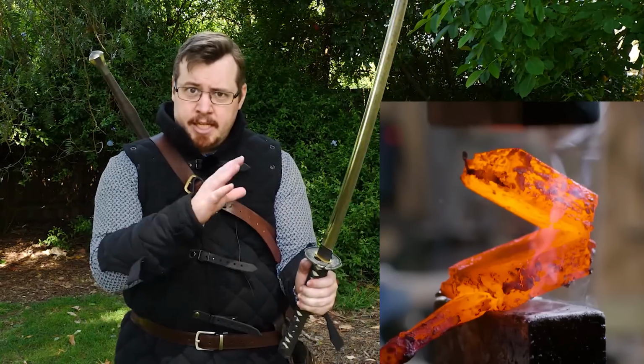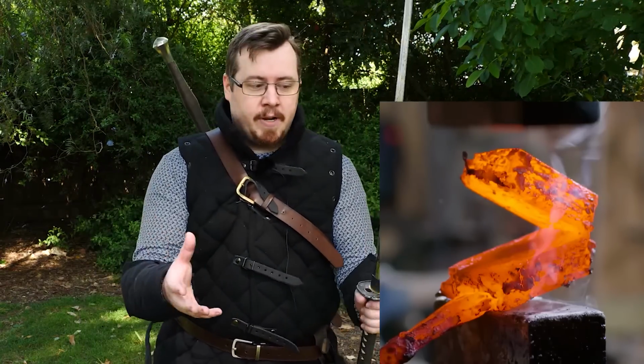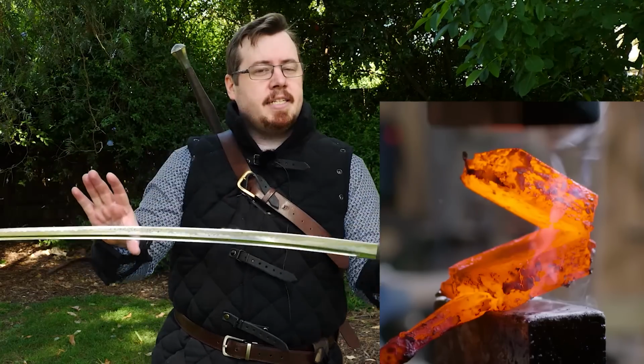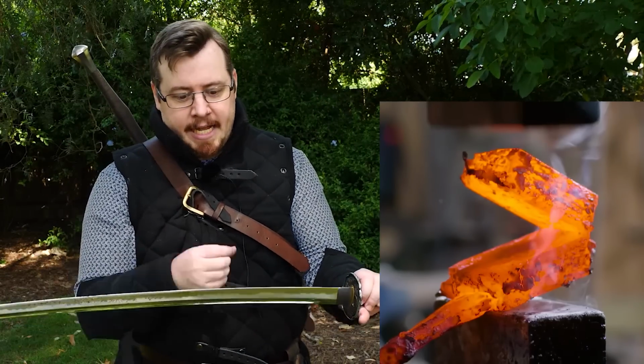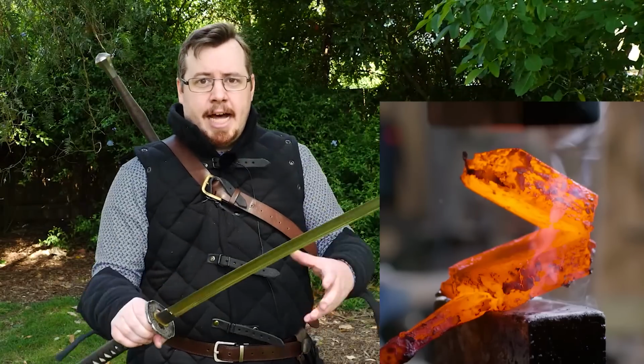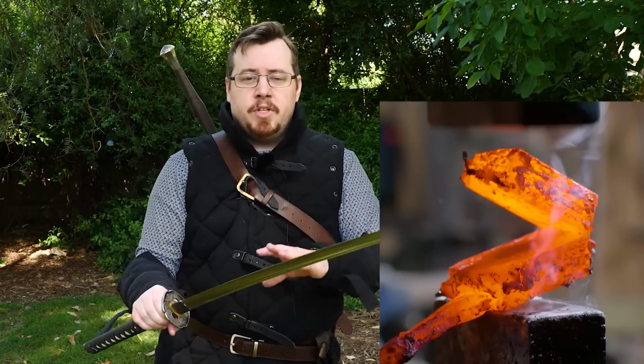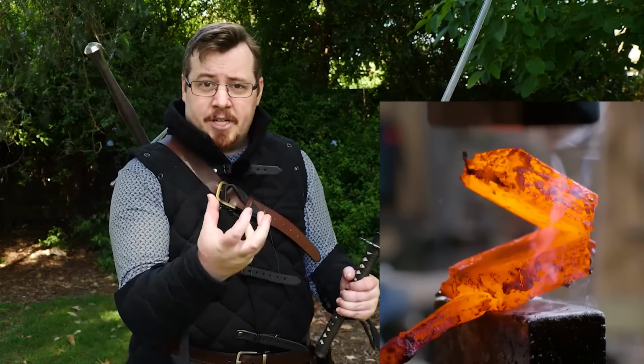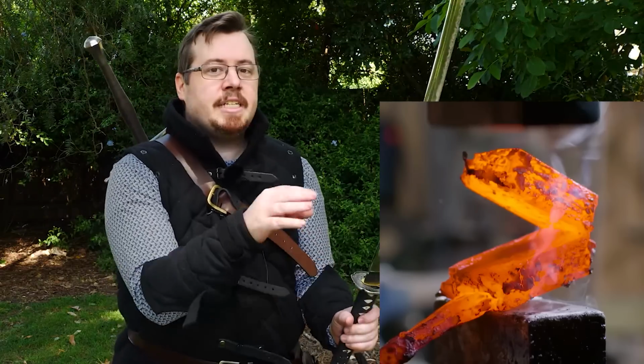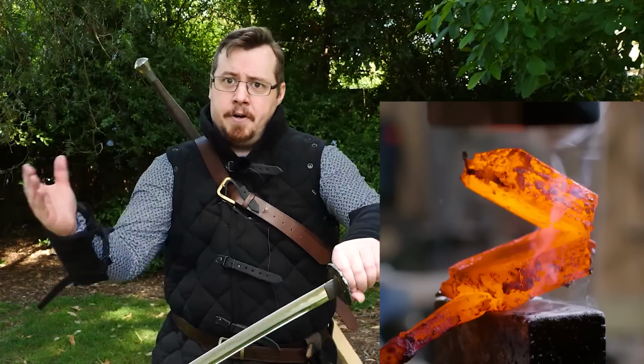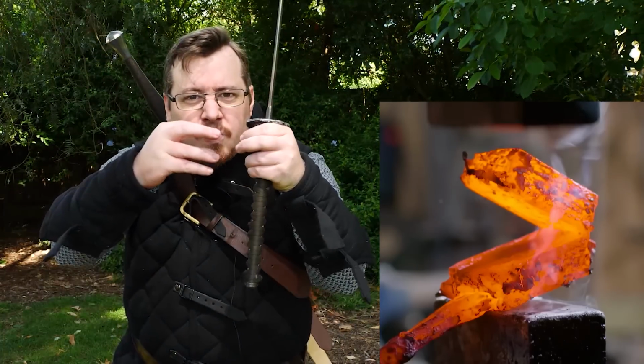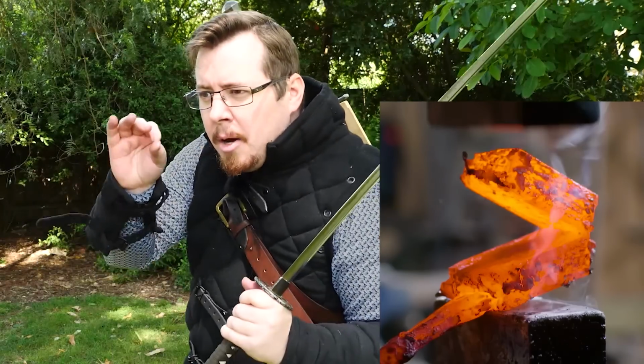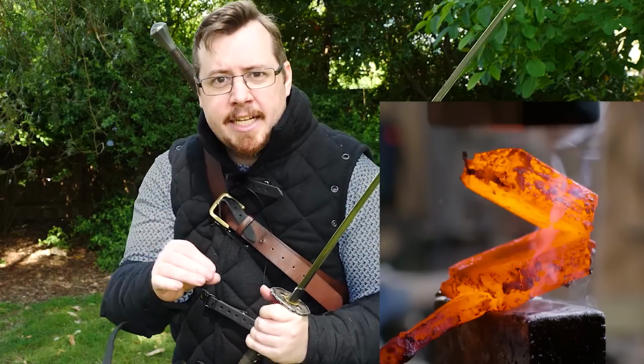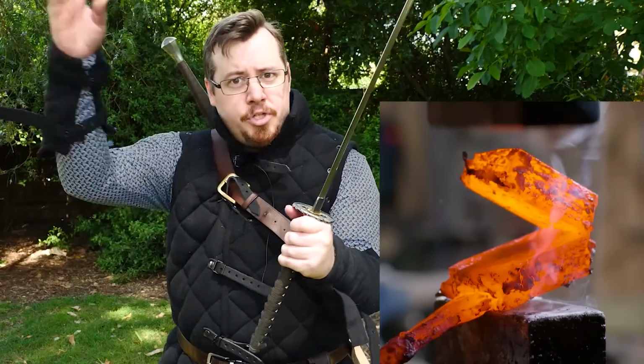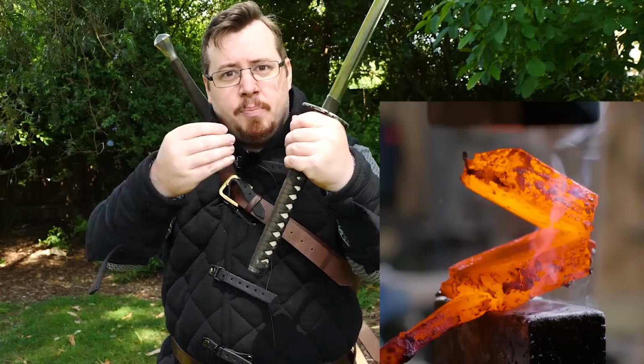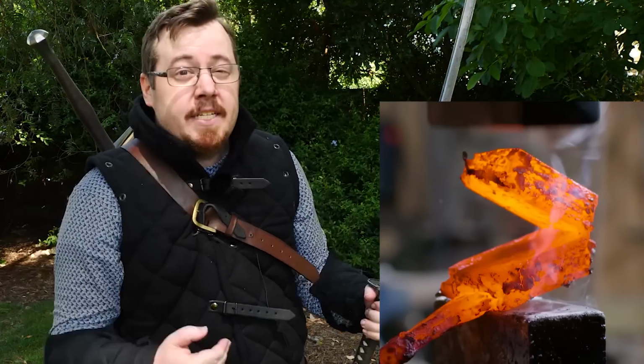How does folding steel remove impurities? Well, this is one. If you have non-metallic inclusions in this steel, they have a lower melting temperature than the steel itself. So when you heat up this block of steel to the point where the steel isn't liquefied, but it's red hot, well, the non-metallic inclusions have liquefied. And when you hammer them down, fold it around and hammer it down, you can squeeze those little pockets of liquid non-metallic inclusions out of the steel. And the more you do it, the more you fold it, the more you squeeze it out to the point where you can actually pop them out of the steel itself.